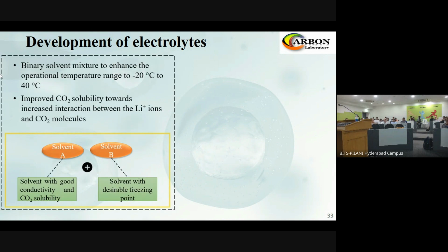Other than this, we are also looking into the development of electrolytes, as I mentioned, because when we are looking at the lower temperature region, the same electrolyte will not be able to work. So we are looking into a binary solvent mixture to enhance the operational temperature range for these metal CO2 batteries from -20 to +40. That is our primary, first goal. And in this range, we are looking for improved CO2 solubility, so that there is an enhanced interaction between the lithium ion and the CO2 molecules. So we are looking for a bisolvent system, where one solvent has good conductivity and CO2 solubility, while at the same time solvent B has a desirable freezing point. That's where we can approach the lower temperature application of this metal CO2 battery.